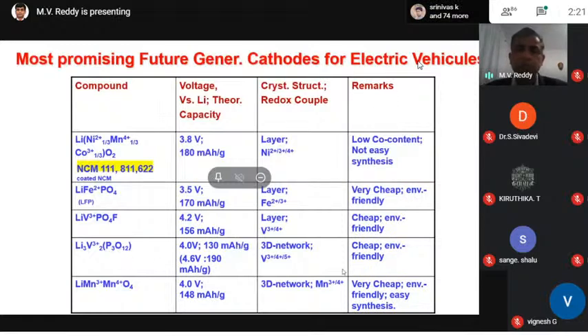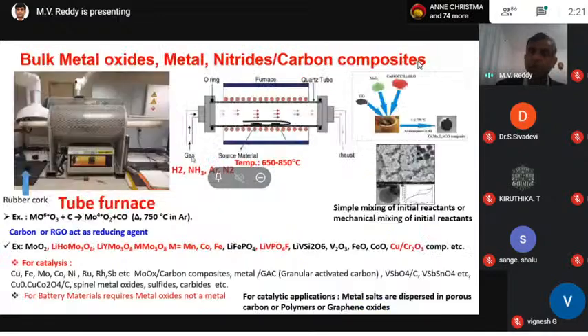So these are very promising cathodes. Among them, presently, I think the more promising is NCM. People are using high nickel-rich materials since they are getting high energy density, in the sense of high capacity, nearly reaching around 200 or 220 milliamp hour per gram capacity, etc. So this is one example.